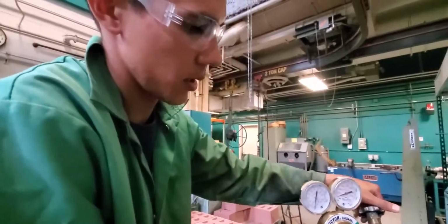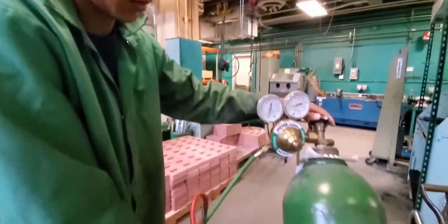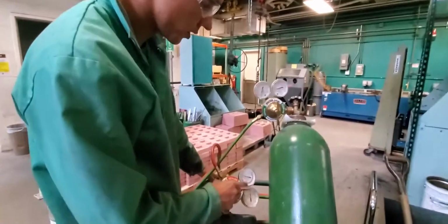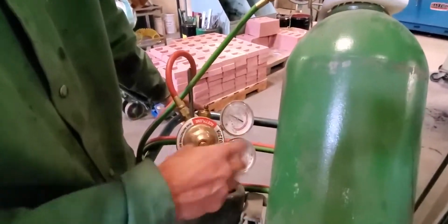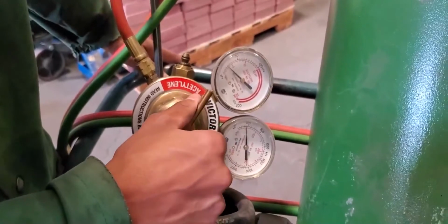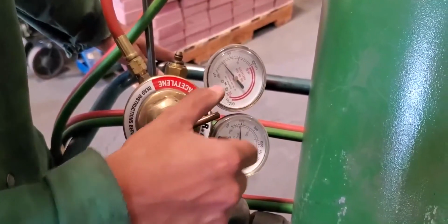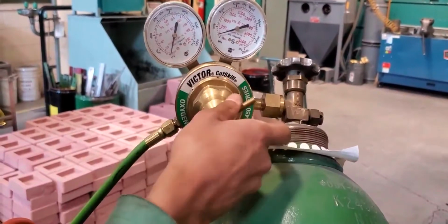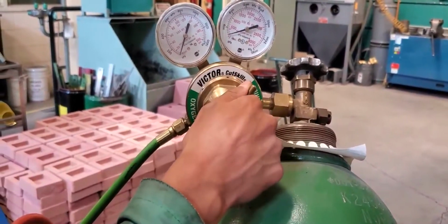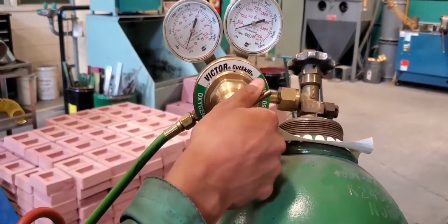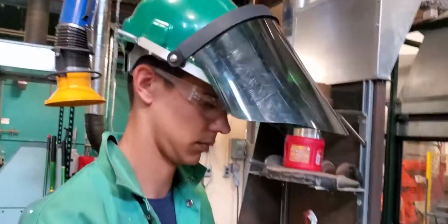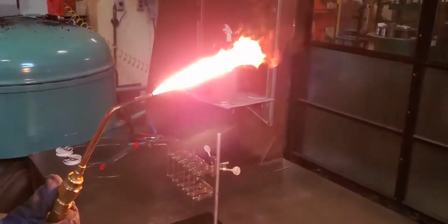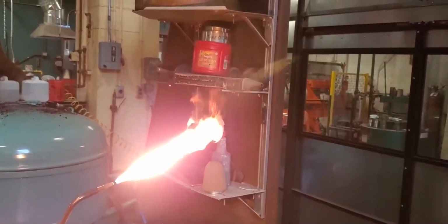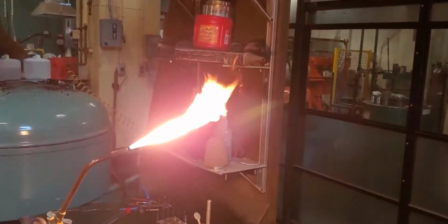There's no trigger on it. So oxyacetylene, not on all the way, just like a little bit. Okay. So I'm using about 4 to 5 psi of oxyacetylene and about 8 to 10 pounds of oxygen. Somewhere in that ballpark. All right, so just igniting the torch. I don't have a lot of soot burning here. We're good.